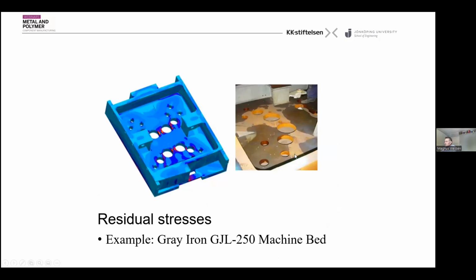So this is the final example. This is about the stress formation in a huge gray cast iron machine bed, where during machining they found they get quite high stresses in this location. The stresses are caused, of course, by releasing stress when you're machining the material, but also the stresses come from the cooling. So if you can control the cooling of the part during the casting, you could design the cooling such that you minimize the stress formation during cooling and also machining later on.